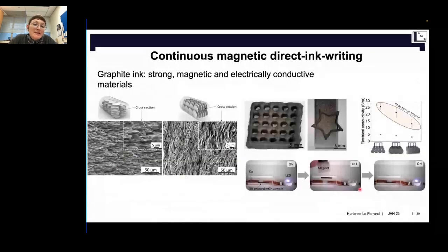The second application is using the same method, but instead of using alumina, we use graphite. And here we can make strong, magnetic and electrically conductive materials with the same quality of microstructure control, as you can appreciate here, of shapes. The materials are also magnetic, but they are also electrically conductive after a reduction at 1050 degrees.